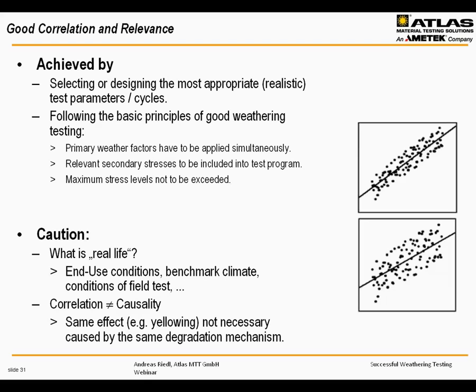If this is 85 Celsius, as measured by, for example, Renault on cars' roofs, then the test also should specify 85 Celsius. If you specify 100 Celsius, then there are two dangers. One danger is that you just throw away good formulations because they fail, but would never fail in reality. The other danger is that you dramatically over-design your products for conditions that will not occur in reality. But be careful, what is real life? This is not commonly defined. Is it end-use conditions? Is it a benchmark climate? Are real life conditions those of a field test?